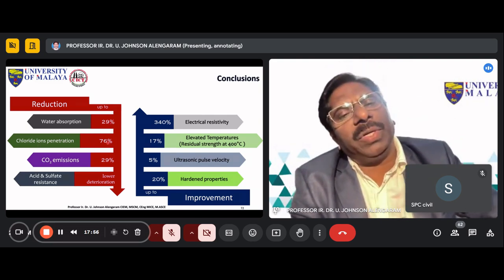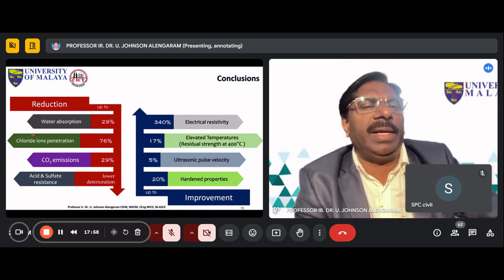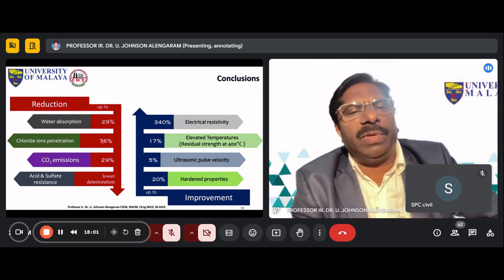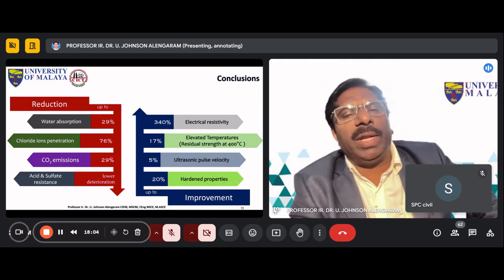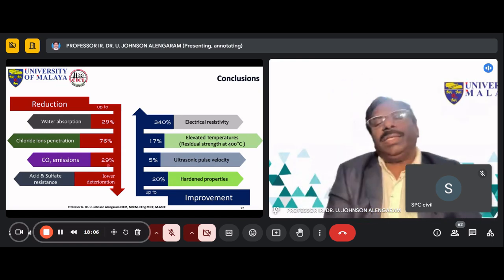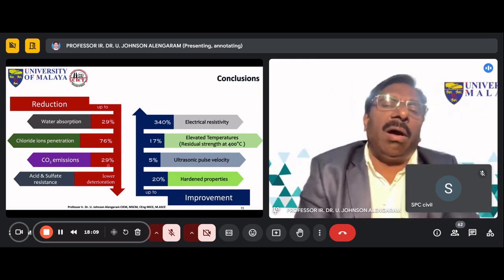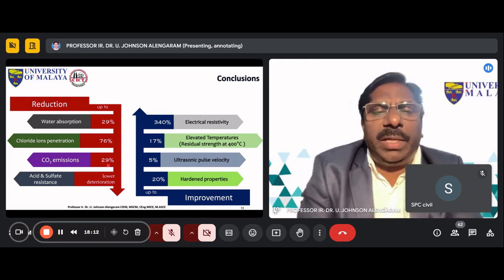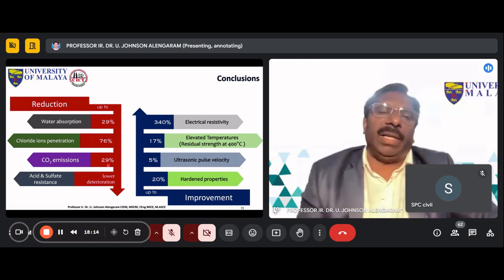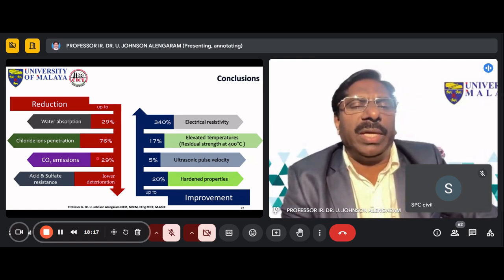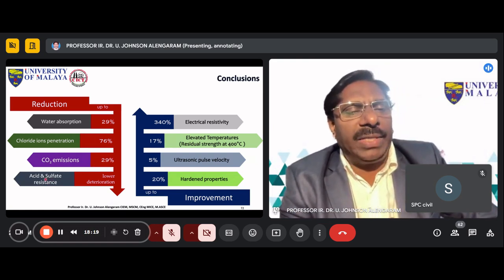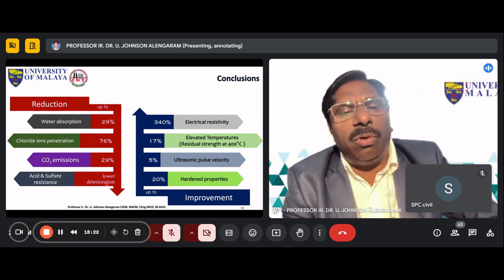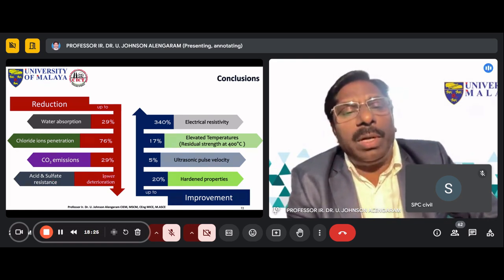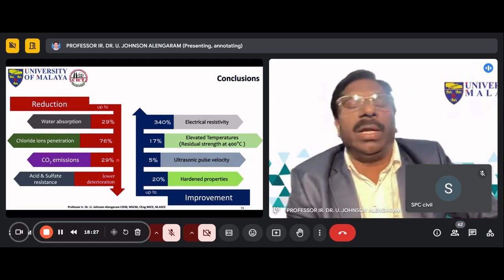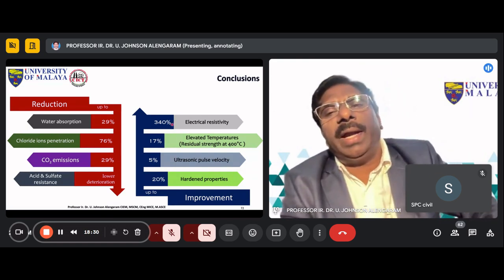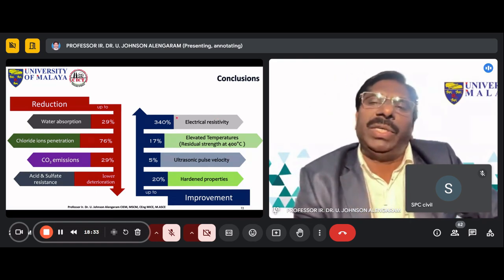The chloride ion penetration was 76% lower because we also calculated the RCPT. So the chloride ion penetration was 76% lower. CO2 emissions were 29% less because we are utilizing supplementary cementitious material, that means non-cement, instead of ordinary Portland cement. Thereby, you see that the CO2 emission is getting reduced. Also, with the acid and sulfate resistance, the deterioration is lower, thereby the durability is good, and this is good for our concrete.